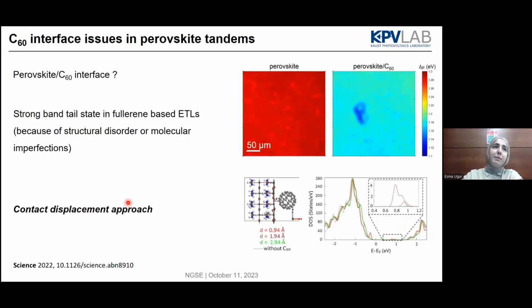For the PIN tandems, we know in the perovskite field that the perovskite C60 interface is the problematic interface. So you can see from that how much voltage loss we could have when we deposit C60 on top of the perovskite.